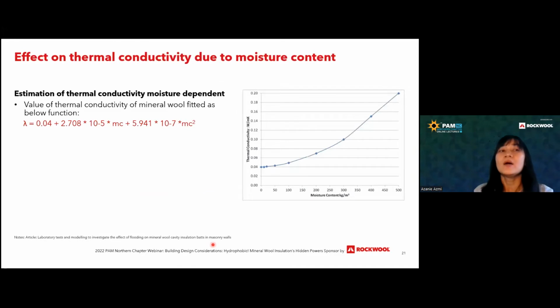Okay, let's look into the effect of thermal conductivities. You know that insulation has very, very low thermal conductivity, around 0.033 or maybe up to 0.04. So that's where in U value for roofing or even under the UBBL or even for partitions, if you want to make sure the U value is very, very low, you need to have insulations. So we want to look into what are the effects on thermal conductivity due to moisture content.